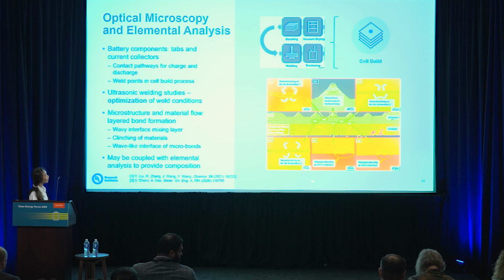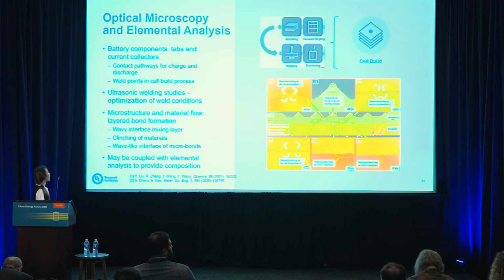Over here, the authors of this paper found that this is an example of a good weld, and they found that there is microstructure and material flow to form a layered bond during the welding process. You can see here some examples of why the weld is good: there's a wavy interface mixing layer, there is some clinching of materials that you can see, and this wave-like interface of the microbonds.